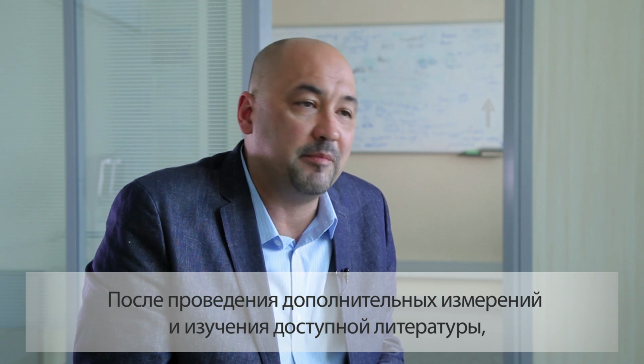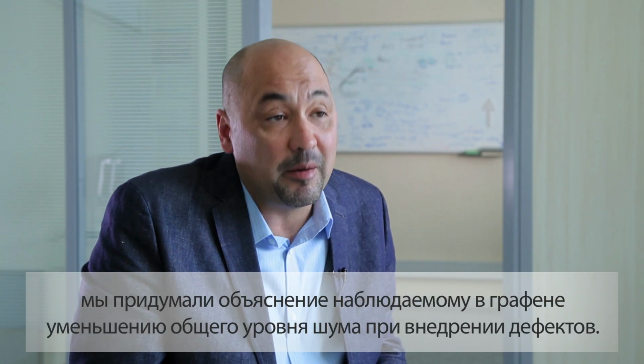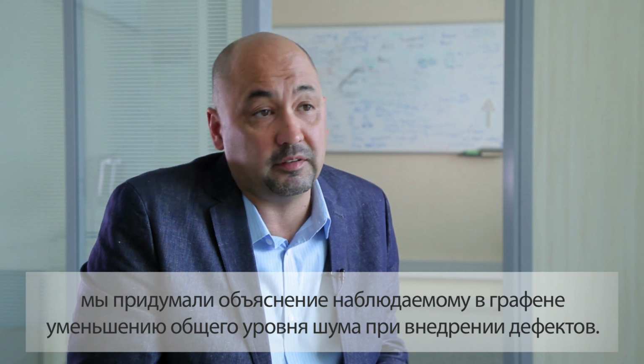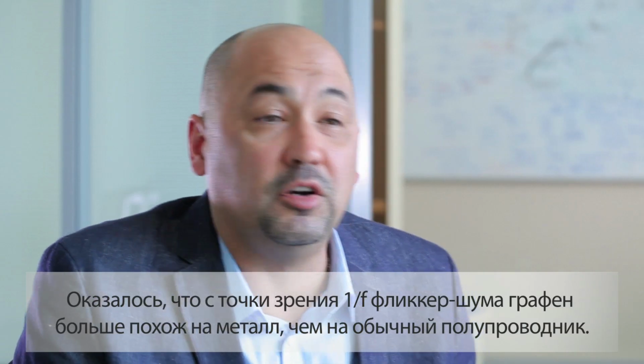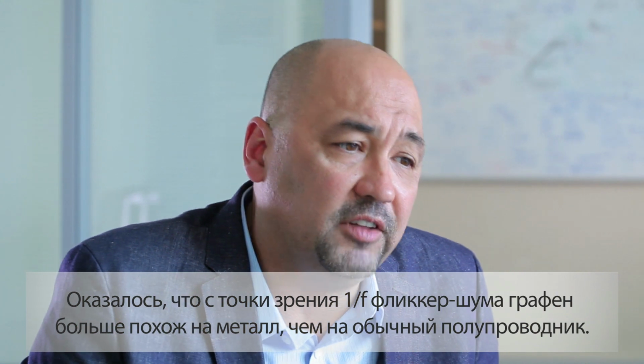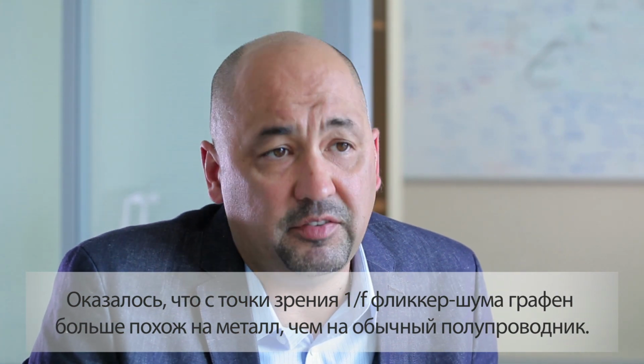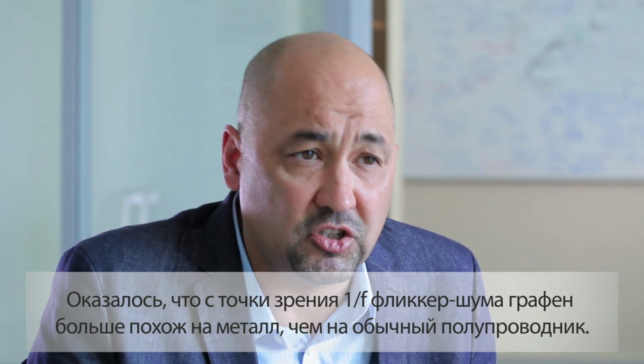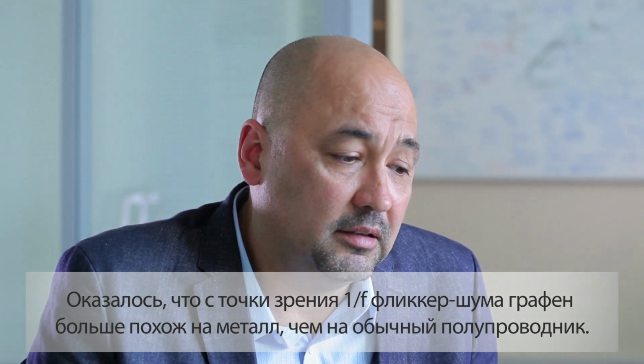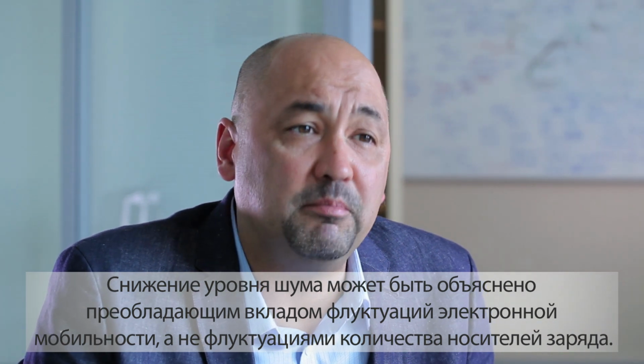After conducting additional measurements and examining the available literature, we came up with the explanation why it's happening in graphene. After introducing more defects, we observe a decrease in the overall noise level. It turns out that in terms of flicker 1/f noise, graphene behaves more like a metal than like a conventional semiconductor. And the decrease in the noise level could be explained by the fact that the dominant contribution to noise is coming from mobility fluctuations rather than from fluctuations in number of carriers.